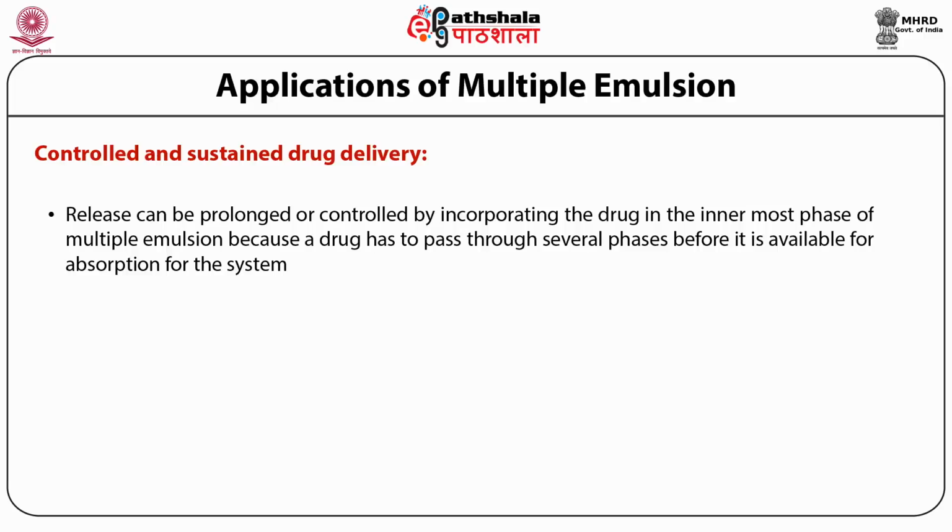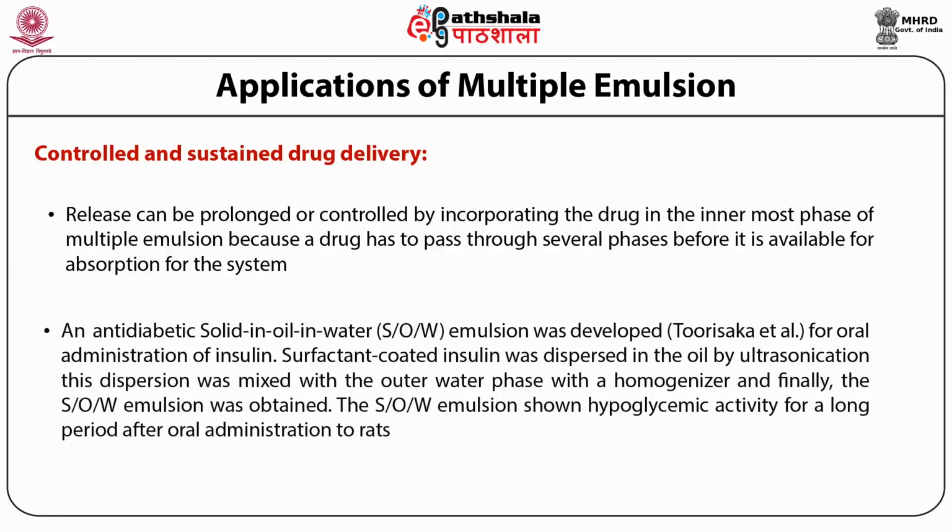Another example is an anti-diabetic solid in oil in water, that is S/O/W, emulsion, which was developed for oral administration of insulin. Surfactant coated insulin was dispersed in the oil phase by ultrasonication, and this dispersion was mixed with the outer water phase with a homogenizer, and finally the S/O/W emulsion was obtained. The S/O/W emulsion showed hypoglycemic activity for a prolonged period of time after administration to the rats.